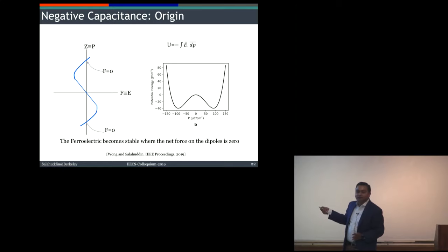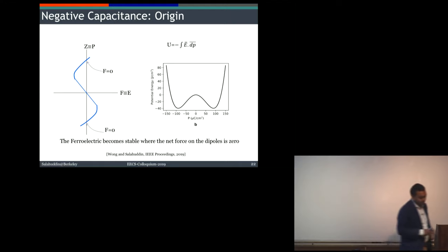If you want to look at the energy, it is simply E dot dP, again, textbook. So you do E dot dP, and it gives you an energy landscape like this. This basically shows that the material will either be stable here or there, and these two stable states are separated by a region where there is an energy barrier. Okay. So now if you look at this again,